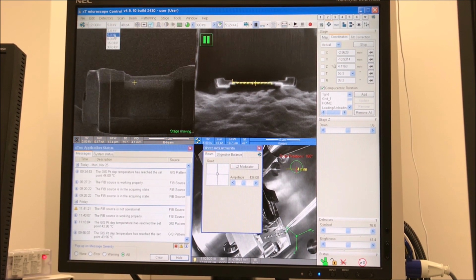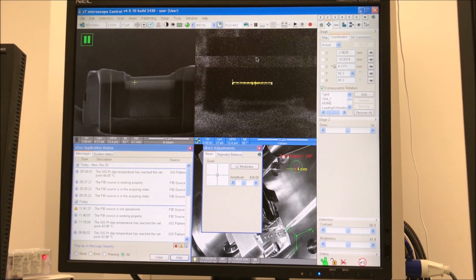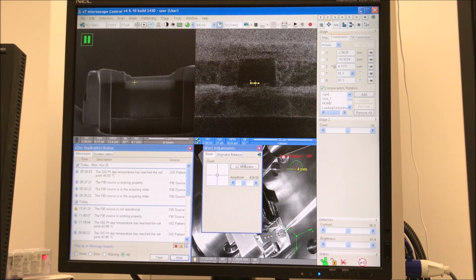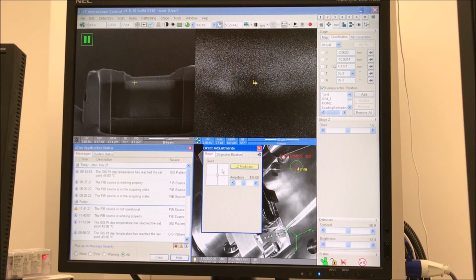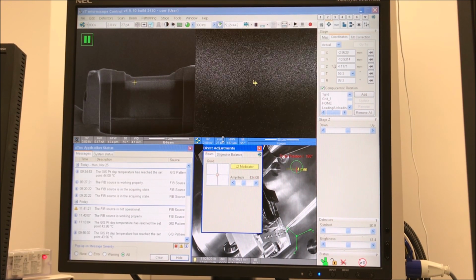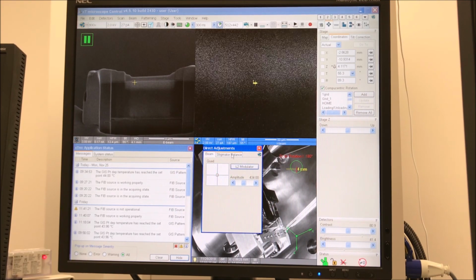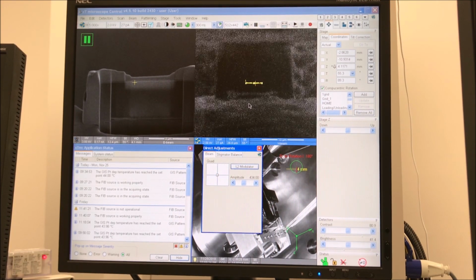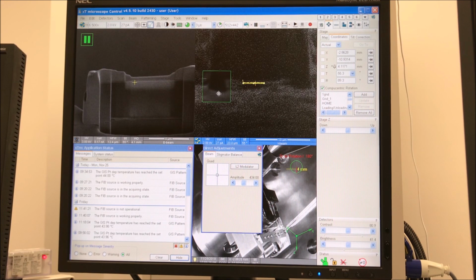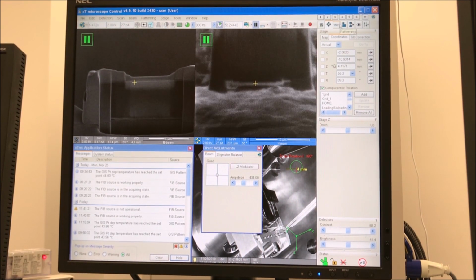The ion beam voltage is going to be reduced to 2 kilovolts. And now I'm tilting +4 degrees away from normal incidence. And I'm going to realign the ion beam with the direct alignments. I think the beam current here is 27 picoamps. So you're going to notice your ion beam image is really, really bad at 2 kilovolts. That's about what you expect because your beam voltage is low and your ion wavelength is therefore very large.